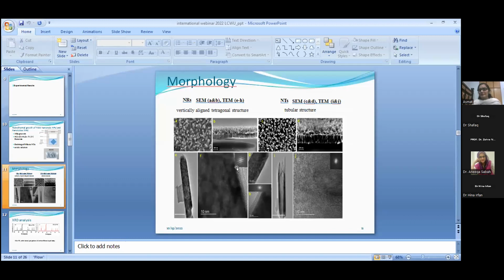One thing is considered for the fabrication of the solar cell. If we fabricate the solar cell, there should not be a direct contact of the perovskite with the FTO. So after the growth of the nanorods, there is a post-treatment of a blocking layer, and here we use a titanium chloride blocking layer, to avoid contact of the perovskite with the FTO. Now you can see this is the blocking layer of TiCl4, which is amorphous in nature, and approximately 3 nanometers. This is amorphous, but the crystallinity of the nanorods is not compromised at the middle part of this nanorod.